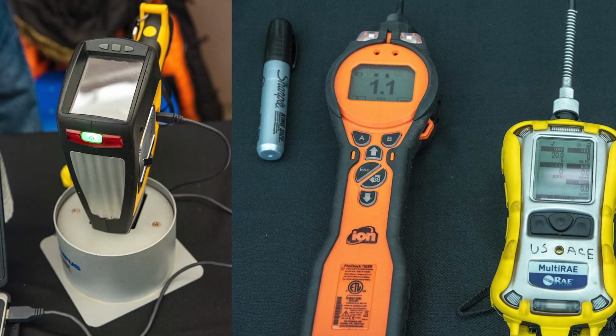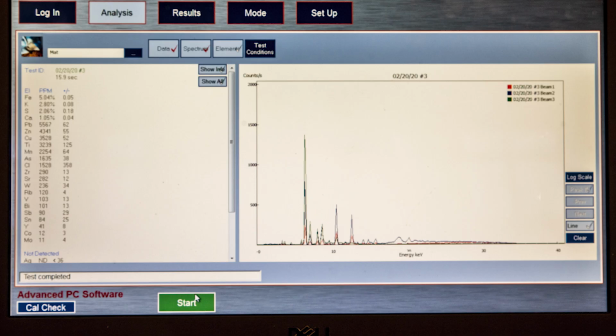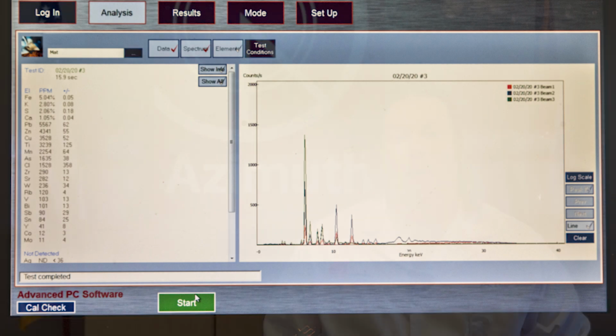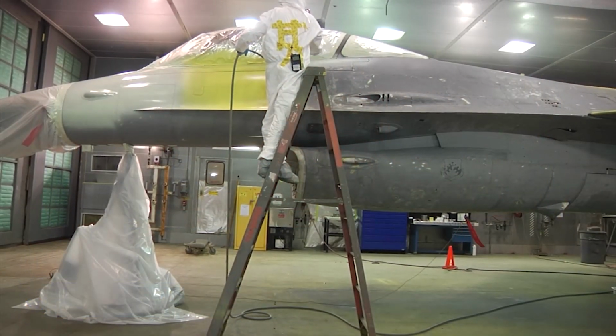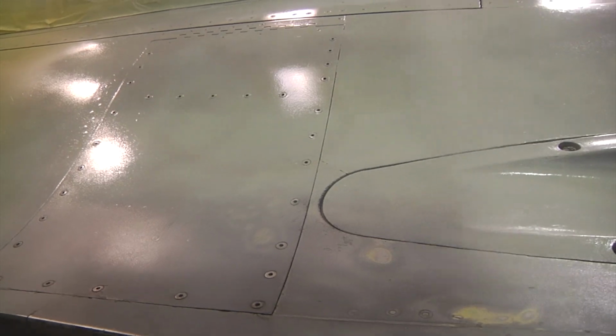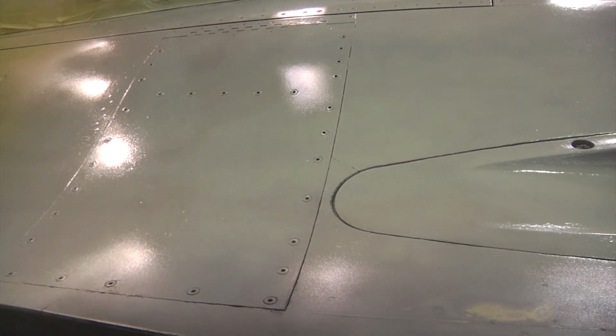X-ray fluorescence imaging also allowed us to observe the full range of the coverage of the coating on a 1-inch squared substrate. XRF analysis displayed a relatively homogeneous coating of a metal oxide across the entirety of the substrate, indicating that this process has the potential to be utilized for covering very large surfaces like that of a large airframe.